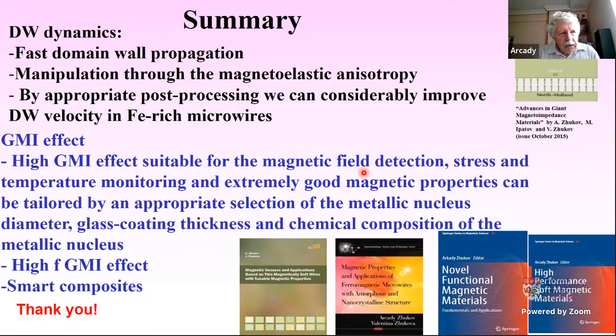In fact, during the fabrication, we have a kind of antenna which measures the impedance. There is a relationship between the signal, which is proportional to the electrical resistance, and then we can monitor this parameter during the preparation.